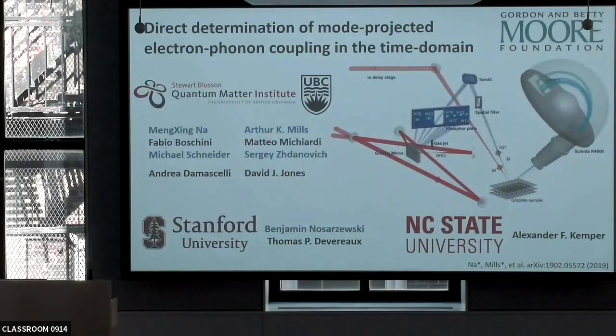So what I've shown so far was all work done at 6 eV. So low photon energy, you're probing close to the gamma point of whatever materials. You cannot really expand all in momentum space. And this has been so far the biggest limitation in this technique. In angle-resolved photoemission, when you use a synchrotron, you can go from, let's say, 0 to 100 and thousands of electron volts, very high energy resolution for the beam. You can map all of momentum space.